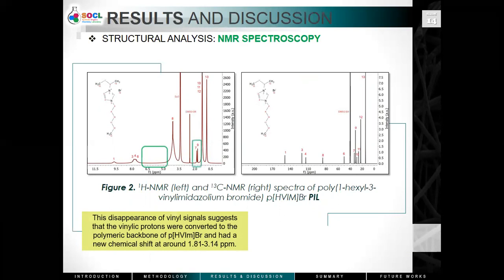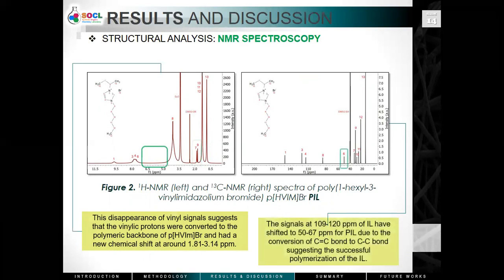This was also verified by carbon NMR spectrum, in which the signals at 109 to 120 ppm of the IL have shifted to 50 to 67 ppm for the polyionic liquid due to the conversion of the carbon-carbon double bond to carbon-carbon single bond, suggesting the successful polymerization of the ionic liquid. The downmost field signals were still assigned to the carbons of the imidazolium ring, and the rest of the peaks were for the carbons of the alkyl chain bonded to the ring.